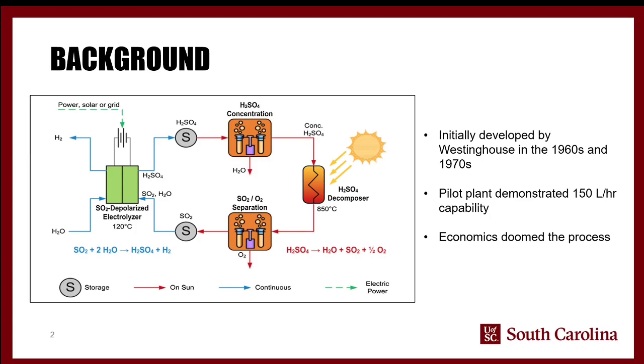So the hybrid sulfur cycle, the goal was to develop a way to produce hydrogen and oxygen from water at a large scale. So most people are familiar with electrolysis of water. And that works well, but you are limited by basically size and the rate at which you produce this. And you have to continuously flow water in, you have to get the hydrogen and the oxygen out. And it works well, but there are ideally ways to do it at an even larger scale. And so one of the ways it was developed was actually from Westinghouse in the 1960s and 70s.